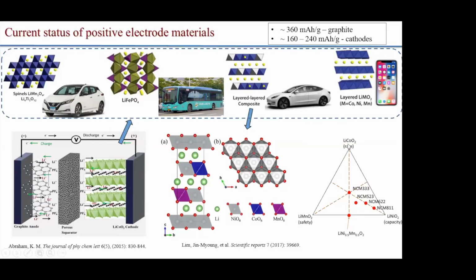What's interesting is if you go to one side, lithium cobalt oxide, you get excellent rate capability. That's why people use it in phones and small form factor, but you compromise on some of the other things. For example, if you have really high nickel, you have pretty good energy density, but you compromise on safety. You need to hit that sweet spot to get the right parameters for an application.